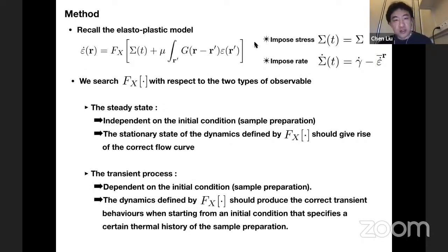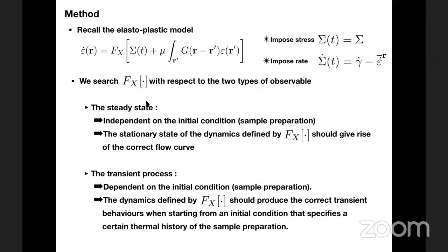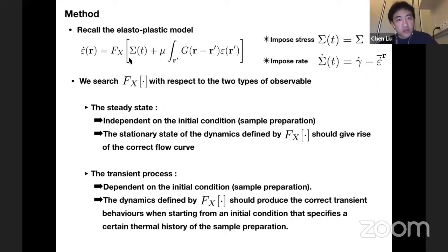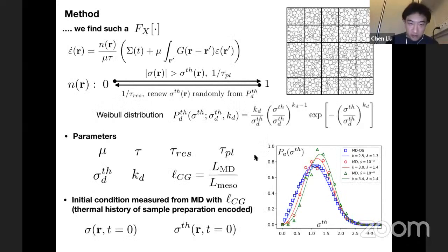Okay, so I continue. This slide is just to say which kind of criteria to follow to search the unknown closure, the function of x. With respect to steady state observables, we want the natural steady state of this dynamics to produce the correct flow curve. And with respect to the transient process, you want this f to take the initial condition that depends on the thermal history and reproduce the correct transient behavior. After a lot of tests, a lot of work, we found a closure that does reasonably good job. So the closure is written in this way.